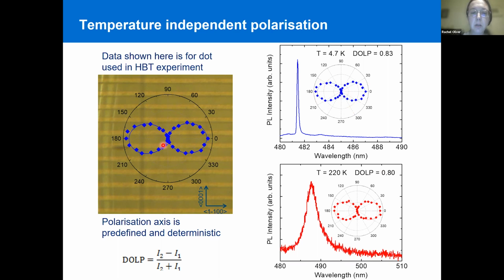And we can also use some of the structures that we grew to help reduce defects in these materials to understand the alignment of the polarization relative to the alignment of the crystal structure. So the polarization axis here is along the in-plane 1-100 direction, and that's common across the vast majority of the dots that we see. So it's not just that the emission is polarized, it's deterministically polarized. We know that all the dots are going to have light polarized in the same direction. We have control over the polarization state.